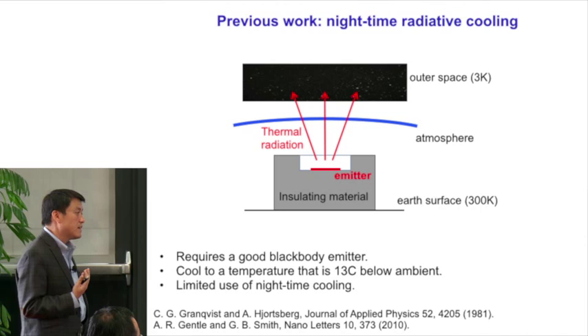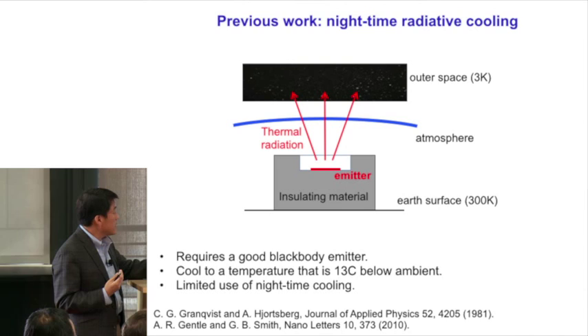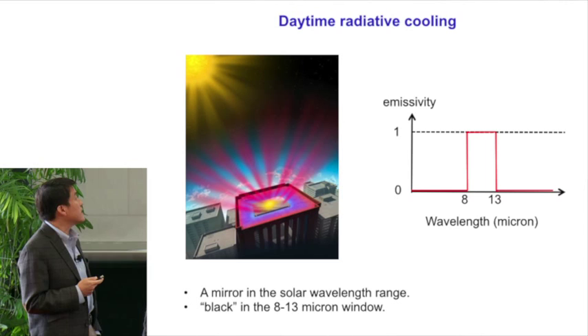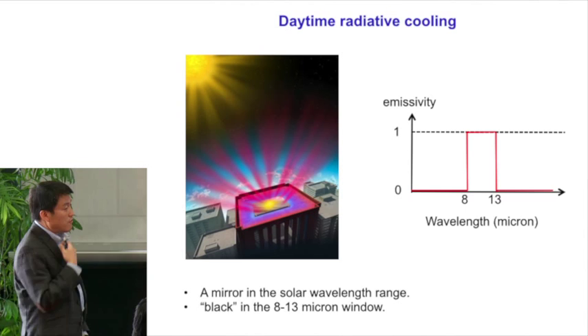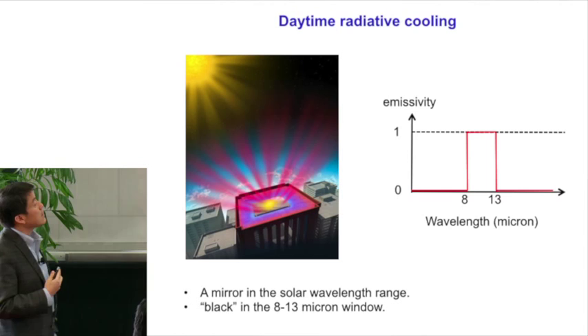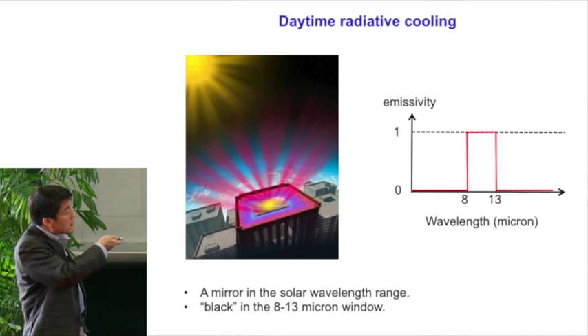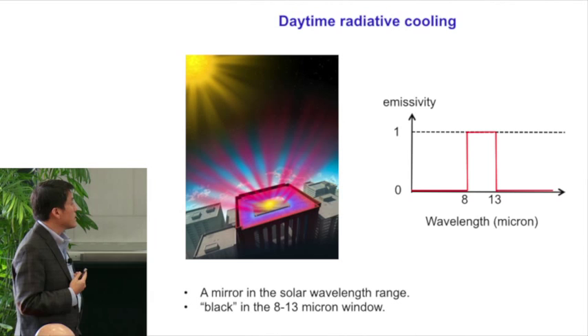So from that argument, it's actually relatively straightforward to imagine what you need to do to achieve daytime radiative cooling. What you would need is an emissivity profile of a material that looks like this: it has no emissivity on the solar wavelength side, so that it's a very good mirror of sunlight, but it is a perfect black body in the 8 to 13 micron window. It emits all the thermal radiation. And remarkably, such a structure has never been constructed before.